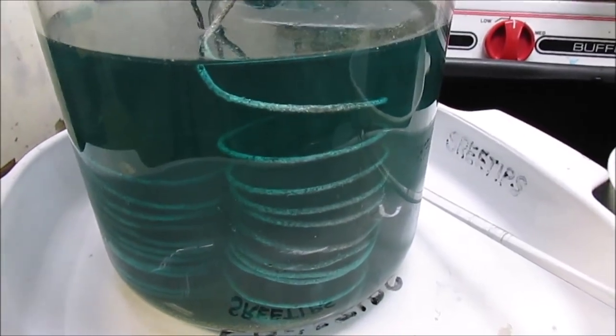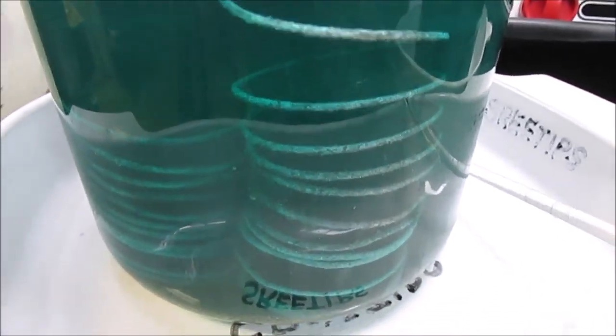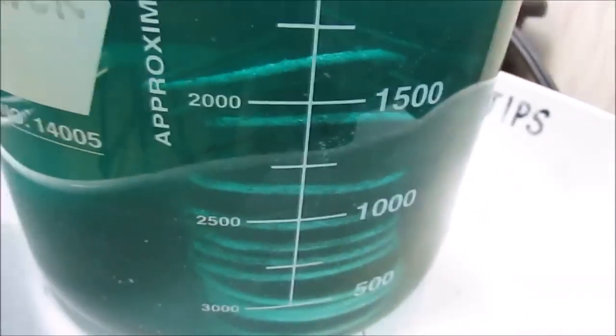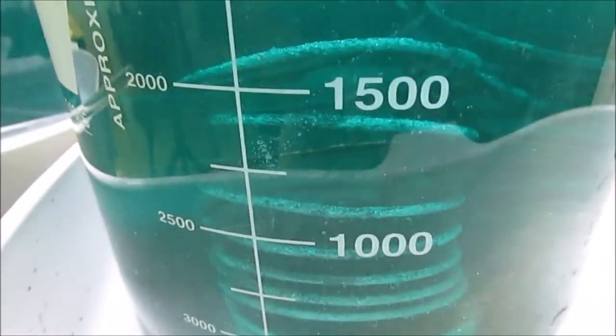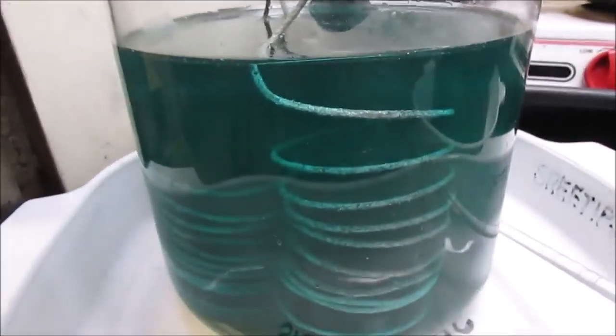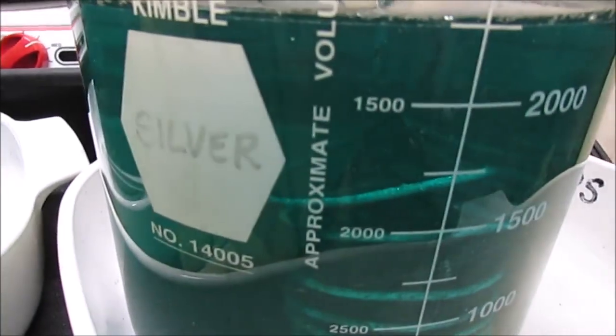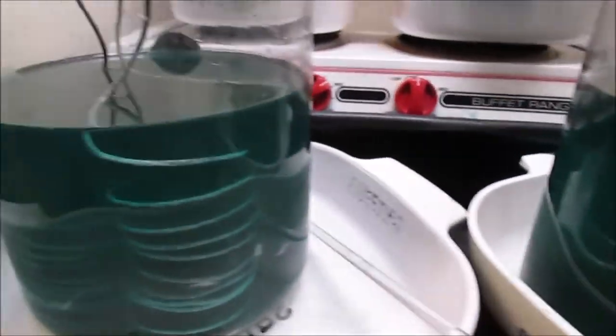Okay, what's happened here is I've added too much of the concentrate. It's formed a passive layer over the copper, and the cementing process is not working. In the next segment, what I'll try to do is add some nitric acid to kickstart it. Some free nitric acid is required for this reaction.